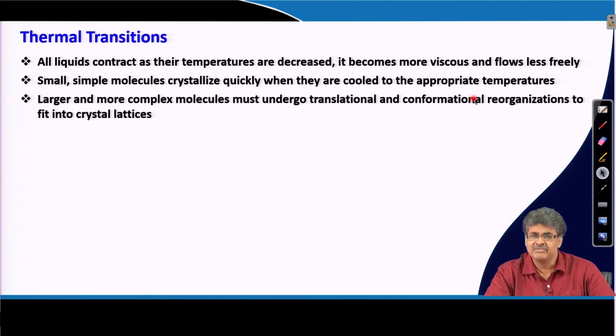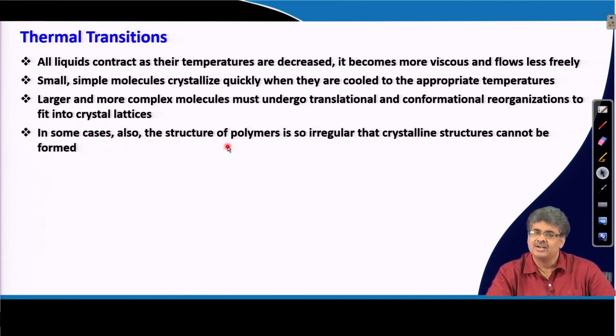But if the molecules present in this liquid state are quite large, like large polymer molecules, and in complex shape, then it is very difficult for these molecules to undergo translational and conformational reorganization to pack in a crystal-like manner. When you form a crystal, the molecules have to come and align themselves in a particular order. Now, if the polymers are very large, then they are all entangled with each other in the liquid state. So, when you decrease the temperature sufficiently, it is still not possible for the polymer molecules to undergo translational and conformational reorganization to fit into a crystal lattice. Also, if the structure of the polymer is so irregular that a crystalline structure cannot be formed,